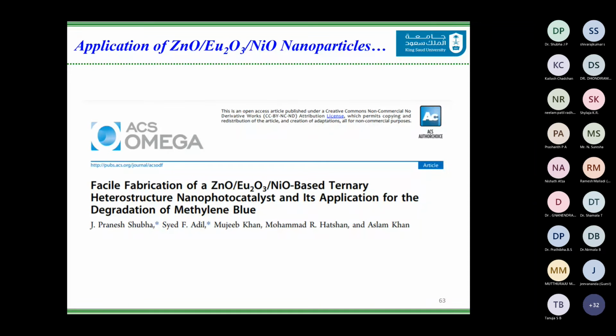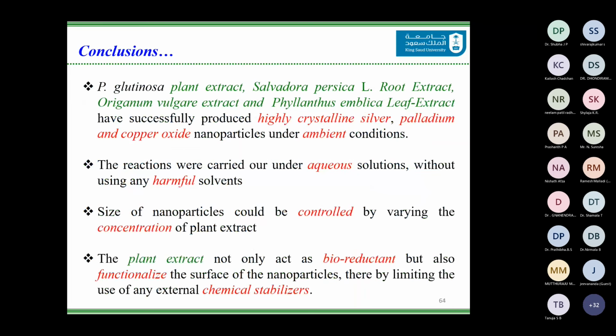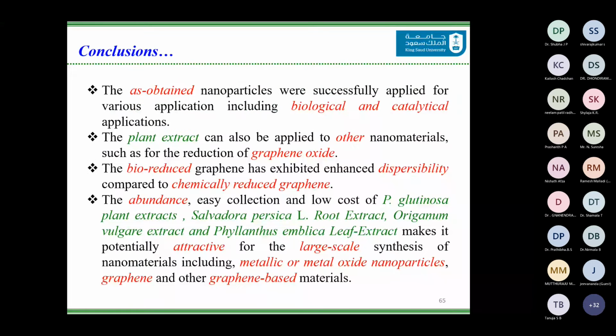So in conclusion, I can say that we have used various plant extracts, and we were able to obtain highly crystalline silver and palladium and silver copper oxide nanoparticles. The reactions were carried out under aqueous conditions without any harmful solvents. The size of the nanoparticles could be controlled by varying the concentration of the plant extracts. The plant extract is doing the dual role of acting as a reducing agent as well as a stabilizing agent,